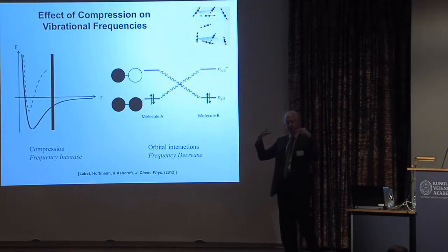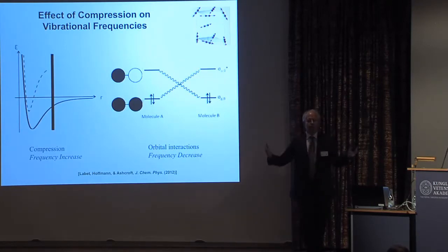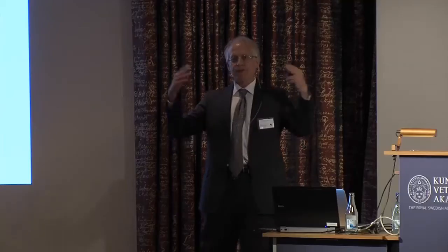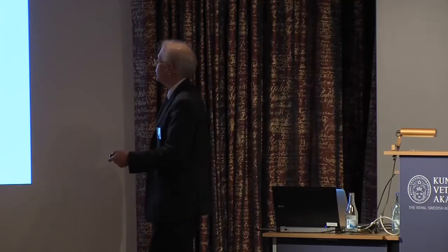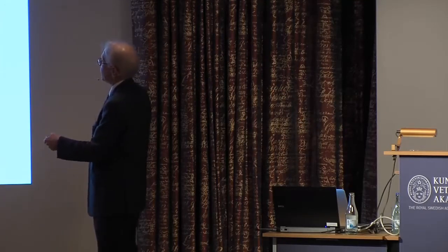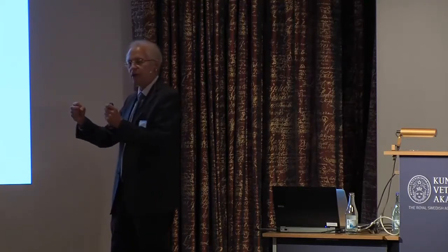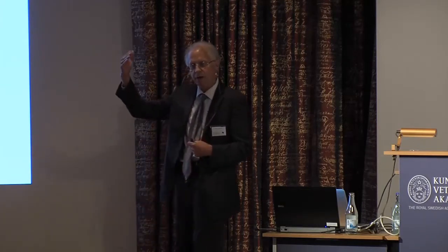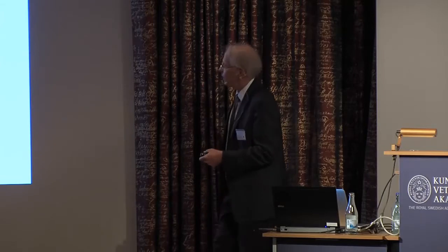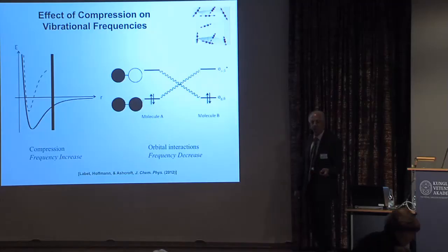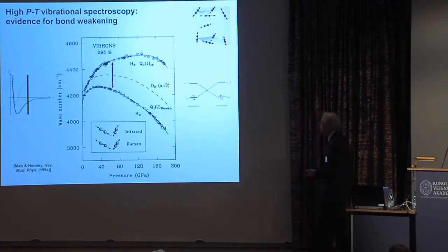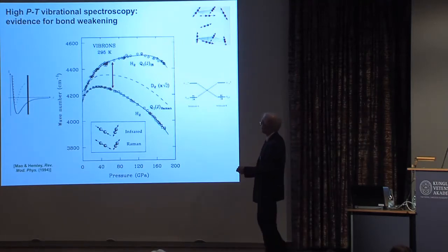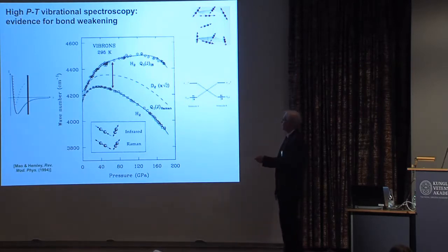So if you think about this in terms of the system wanting to form an extended structure, say like nitrogen, there's the bonding and the antibonding states, and with increasing pressure, there could be mixing of the antibonding states into the ground state, and this would cause a frequency decrease. So what do we observe experimentally? Well, we observe both. With increasing pressure, you see this increase over here in frequency, and that's followed by a decline on the right side.